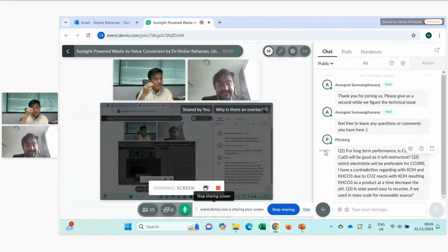This is a very good question actually, for long-term performance. So copper 0, copper 1, especially, we don't talk about copper 2 because it gets reduced, but sometimes people argue about subsurface oxide, the presence of subsurface oxygen under copper. So it depends on the connectivity of the copper material with the substrate. But generally, for long-term performance, if we make copper oxide derived copper, the nanostructure comes on the surface, that is quite stable, and that is quite good for the long-term performance.